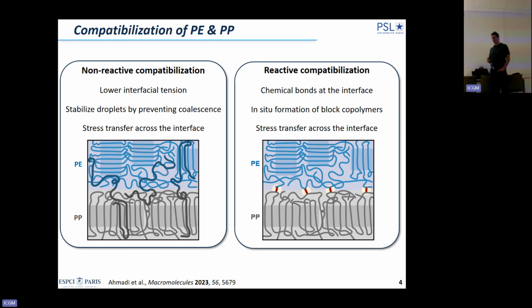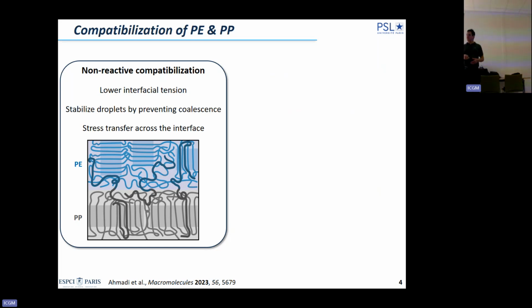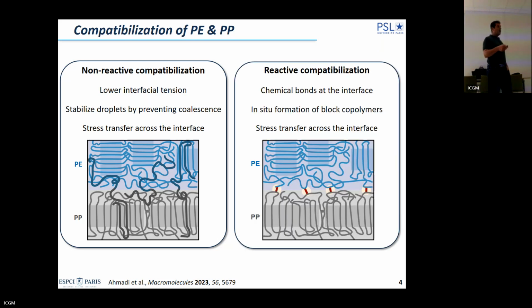And another solution is reactive compatibilization. The first case is based on physical interaction, co-crystallization mainly, but you can also think about van der Waals interaction, depending on the kind of polyolefin. Reactive compatibilization is to create chemical bonds at the interface, and this chemical bond will allow the stress to be transferred. So one way to do this is to create in situ block copolymers. I will show you one example of the two.